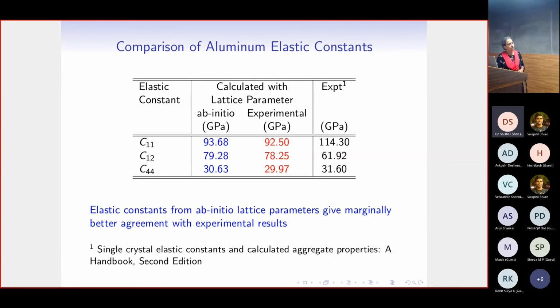So we thought, okay, maybe it has to do with there being some error in the original lattice parameter prediction from ab initio. So let's not work with the ab initio lattice parameter, but let's start with the experimental lattice parameter. And we still do the calculation of the elastic constant by doing this strain method, but now the strain is applied to the experimental lattice parameter. And with this, these are the numbers we got.